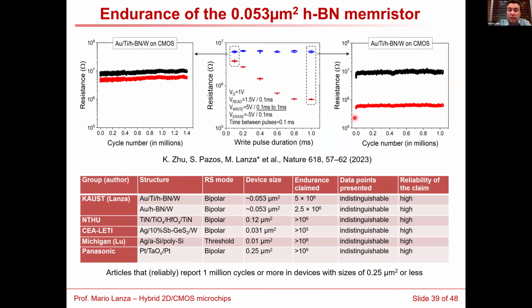The most surprising thing for us was the endurance. Because, you know, in such small devices, it's very difficult to get very high endurance. If you check in the literature, you will find many papers that show high endurance. But most of them are in large devices, where it's much easier because you have a much larger amount of defects. And this is a defect-enabled switching mechanism. Our devices are very small. We still see 1.5 million cycles. Well, in fact, it's 2.5.